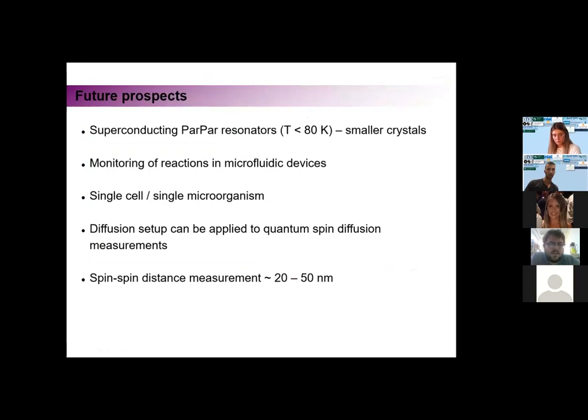Okay, so this is some of the work we did. We have some more ideas we thought about in our future prospects. Instead of copper, we can use a superconducting metal to fabricate our resonators, and then maybe we can measure smaller crystals, maybe around 1 micron, maybe in the future nanocrystals. But for this, we have to reach the critical temperature of the superconducting metal, which is usually lower than 80 Kelvin, at least in the case of the metals we work with.